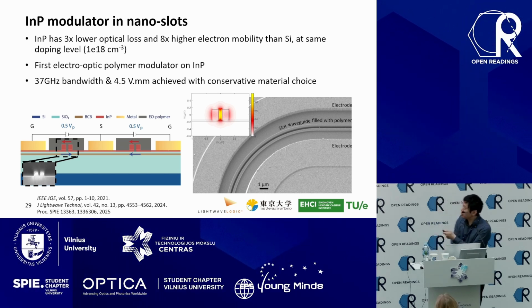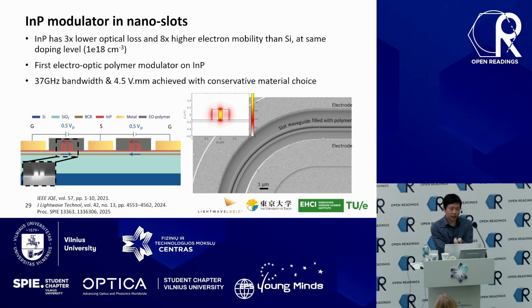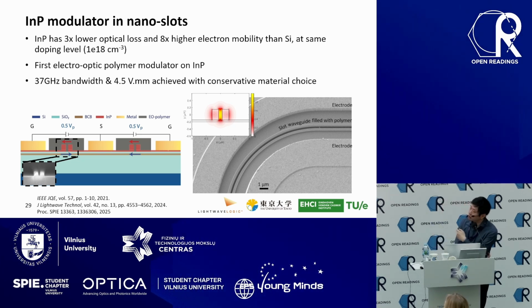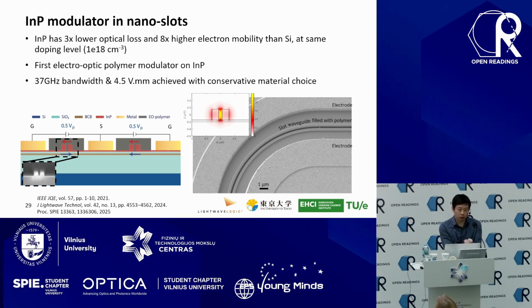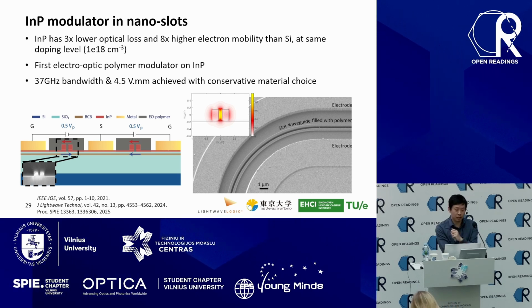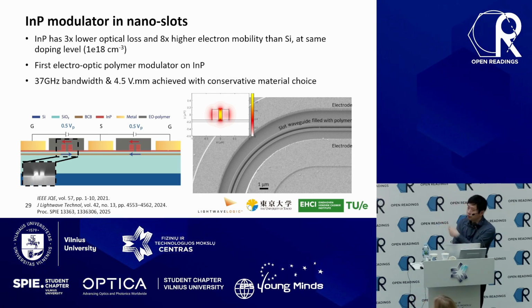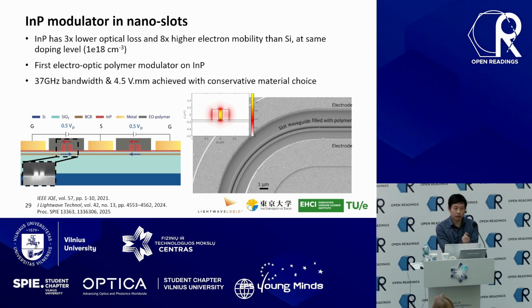And we are also motivated to see how indium phosphide can play better than conventional design in silicon, because indium phosphide, in principle, when doped at the same level, should have a much lower optical loss and much higher electron mobility, which are needed for optical modulators. So this is the first device we have fabricated, very nicely defined nano slots filled with electro-optic polymer, and we achieve about 40 gigahertz bandwidth.